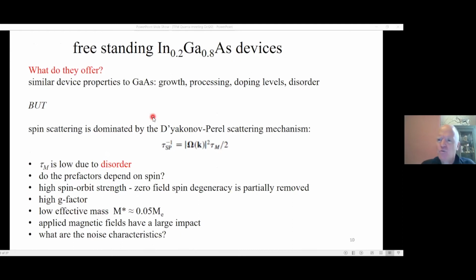So coming on to what I've been doing and why I've started to look at InGaAs for these systems. What does InGaAs offer? It's got very similar device properties to gallium arsenide. It's easily grown. The Cavendish Laboratory has great MBE chambers for growing this. We can process it. We can introduce disorder through doping, delta doping. But also we've got spin, and in the localization problem, spin is usually ignored. It's usually a factor of 2 somewhere, but it's usually ignored. So my interest was, let's put spin back into the problem.